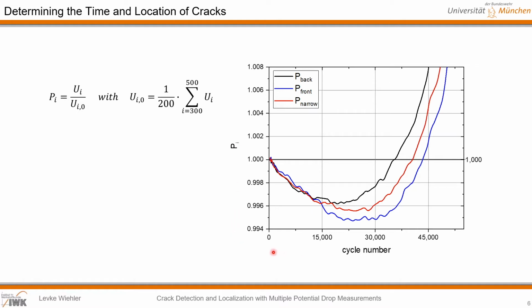What is striking about the run is the decrease of all potentials within the first 20,000 cycles. As I explained earlier, the potentials should rise as soon as a crack is initiated. Because of the decrease, we are not able to detect a crack by only looking at the run of the relative potentials. By the way, this drop is explained with a decrease of the temperature after the beginning of the test.